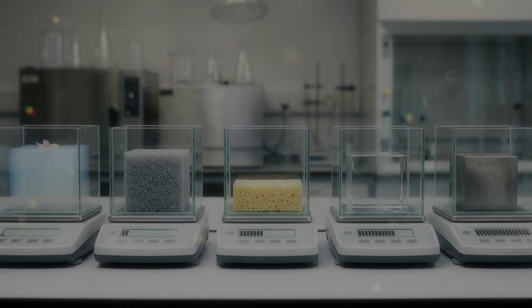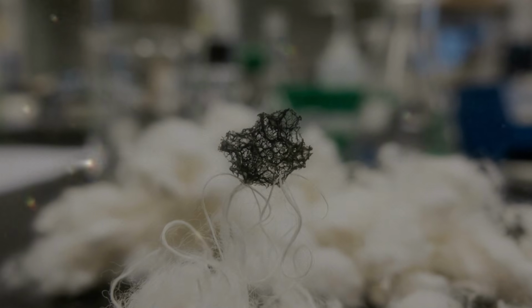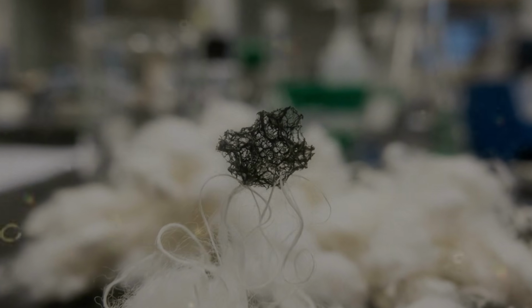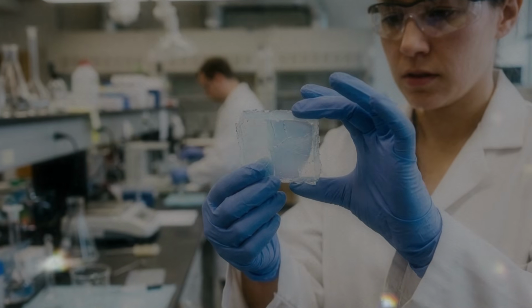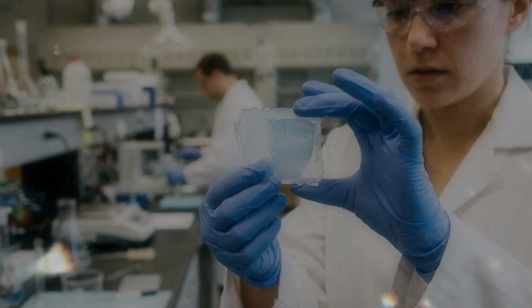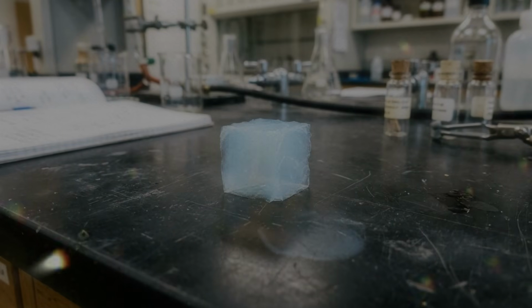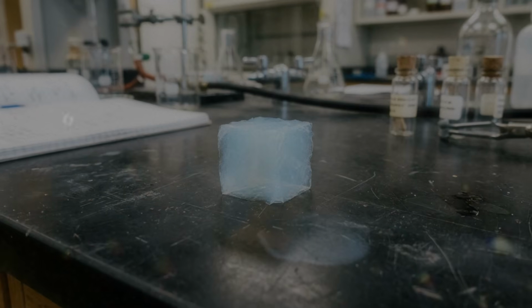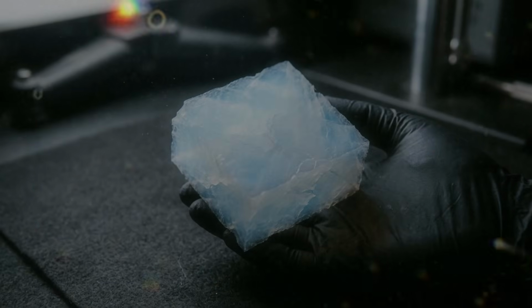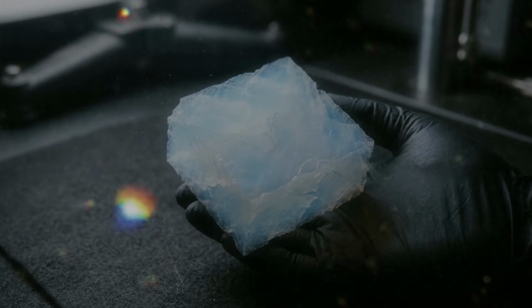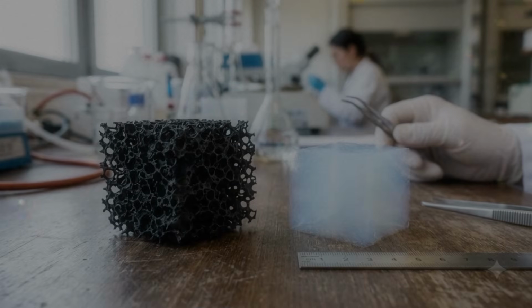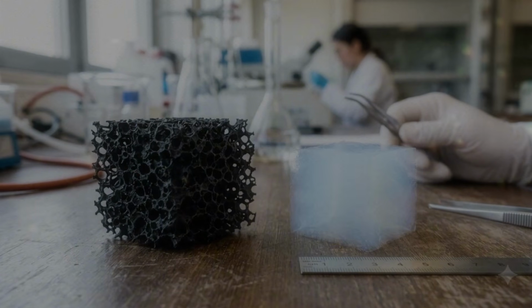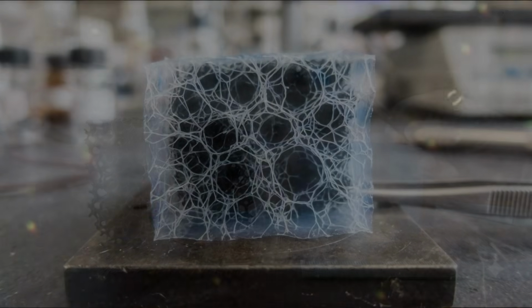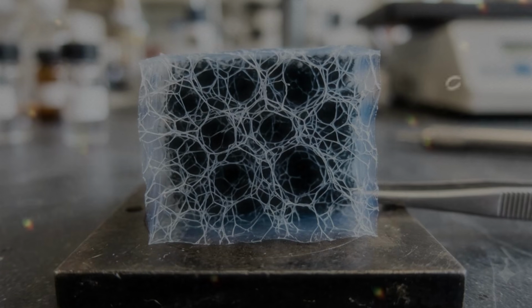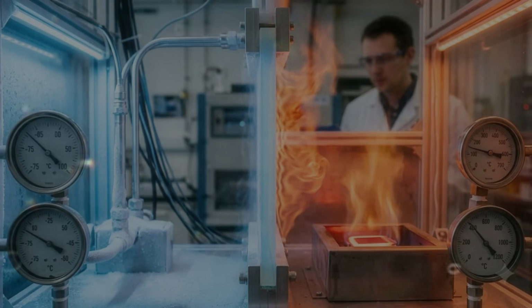When the material is compressed, the largest and weakest pores close first. The sample may feel soft at the beginning. As more pores collapse and more walls contact one another, it becomes harder to squeeze. This gradual increase in resistance allows the aerogel to absorb mechanical energy. Instead of sending the entire force straight through, it uses that force to bend walls and close pores. Conventional foams use the same general principle in packaging and protective equipment. Aerographene can achieve similar behavior with far less mass. It may also remain electrically active while deforming, which allows one object to absorb force and measure that force at the same time.